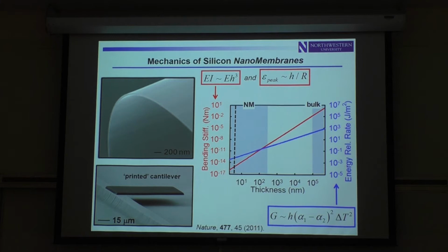So silicon nanomembranes are in fact very, very bendable in the sense of having a low bending stiffness. They can also bend to a very tight radius of curvature because of another attribute in thickness scaling, which is that the peak strains associated with bending a slab of material like that to a given radius of curvature R decrease linearly with the thickness. Now, silicon fractures at about a 1% tensile strain, so you can bend a silicon nanomembrane to a very tight radius of curvature without reaching that fracture level. And so as a consequence of that thickness scaling, silicon nanomembranes are floppy and they're flexible.